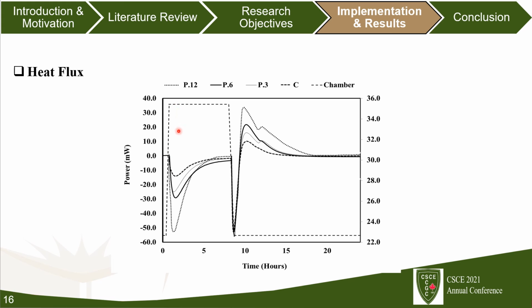When the temperature of the chamber is above the phase transition temperature, the microencapsulated phase change material incorporated in our sample started to absorb the heat, as you see in this figure, through an endothermic process for the first 5 hours. And during the cooling down period, an exothermic process took place, and the phase change material started to release the absorbed heat over the next 9 hours. So this experiment shows that incorporating phase change material can significantly improve the thermal performance of our mortar.